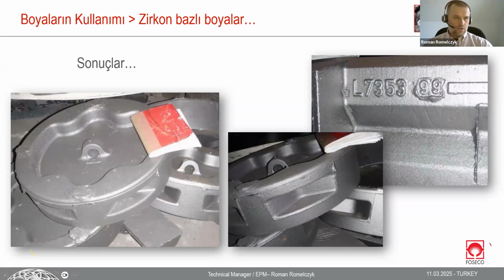What's more here, I can say that if you see these pockets on the core, originally it was used chromite sand for it, but because of usage of impregnation coating, these cores were made with fresh silica sand. It was a Furan process. Silica sand, it was used Zirkon, so impregnation coating, normal zircon top coat, and we were able to receive that kind of results.